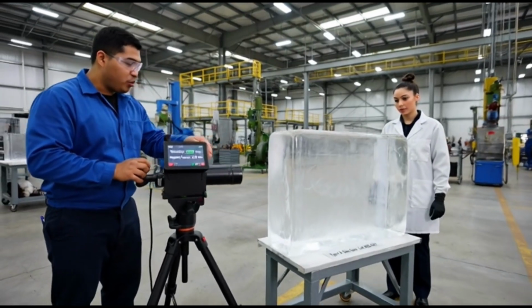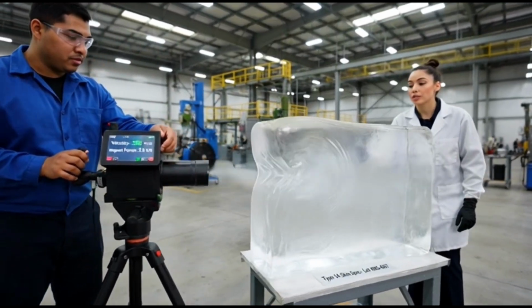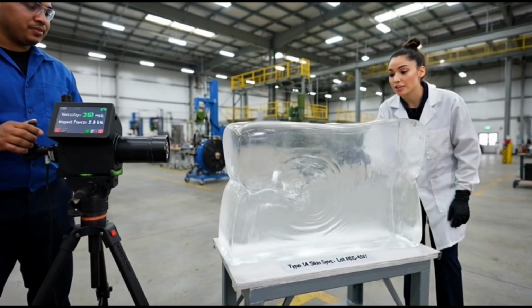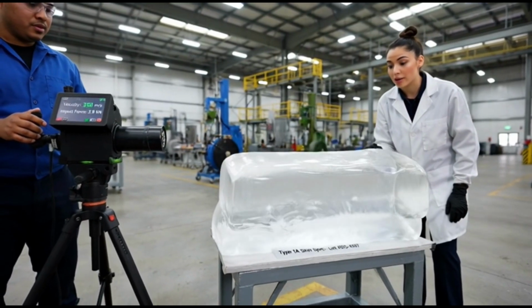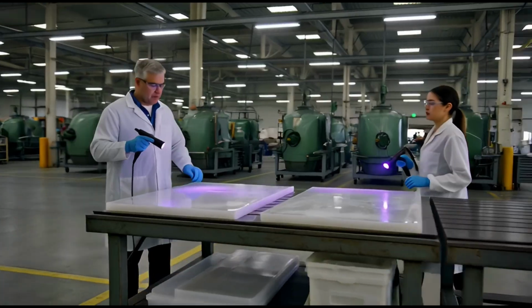Ready for the test? Type 1A gel block aligned. Confirmed. Proceed with the shot. Firing now. Impact registered. Forces 2.8 kN within spec. Excellent. That's a pass. Shine it here.